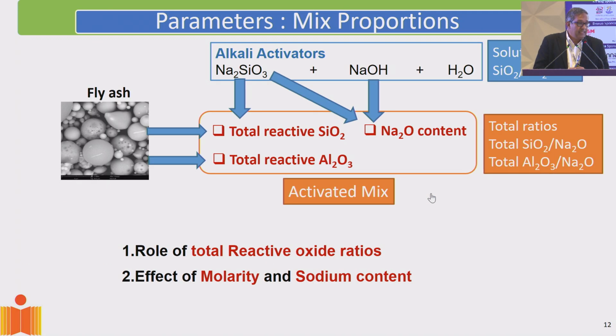Now, this is the key slide that we basically came up with, to use the fly ash in a very effective manner, particularly for producing geopolymers. Fly ash, if you look at the two arrows coming out of there, contributes reactive silica and reactive alumina to the system. To this, you typically use activators, which are sitting in the box at the top. You use water glass or sodium silicate, sodium hydroxide, and water. Sodium silicate contributes silica and sodium to the system. Sodium hydroxide contributes sodium to the system. And then, of course, you have water that balances the pH of the system.